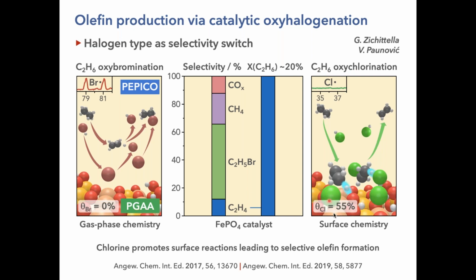You have a high coverage of chlorine on the surface, and because you are confining all the reactivity on the catalyst surface, it's much easier to control the selectivity, to the point that by ethane oxychlorination, ethylene selectivities of 100% can be attained. So that really shows the effect of the halogen in determining where the chemistry is taking place. Left side, gas phase, bad. Right side, surface, good.